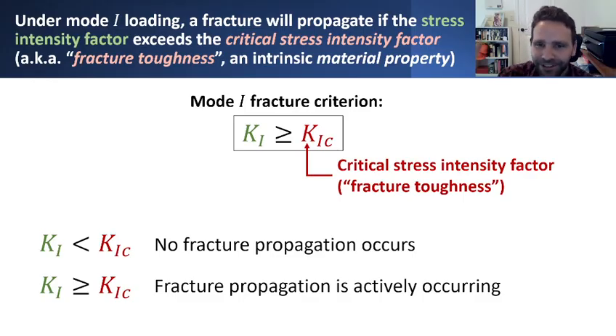So again, fracture occurs, we say, when the stress intensity factor exceeds this critical stress intensity factor, or the fracture toughness, a material property. If, however, I load the material up and I find that my stress intensity factor is below this critical value, then I say, oh, well, I'm fine. There should be no fracture occurring, and if there was a crack there, then the crack shouldn't grow. It shouldn't increase in size or length. So that's good. If you're trying to design some structure such that it doesn't fracture, clearly you want K1, the stress intensity factor, to be less than K1C. That's your criterion to evaluate will it fail or not.